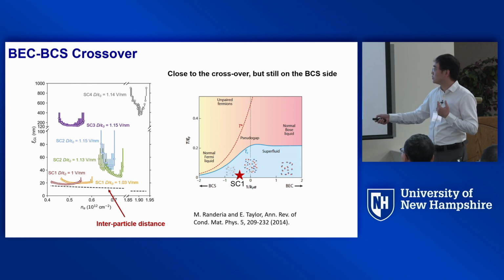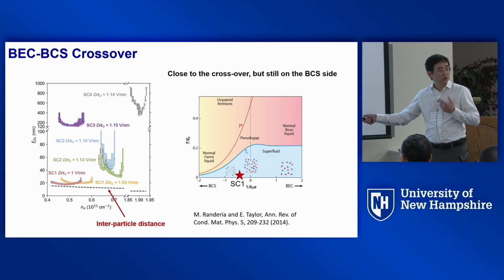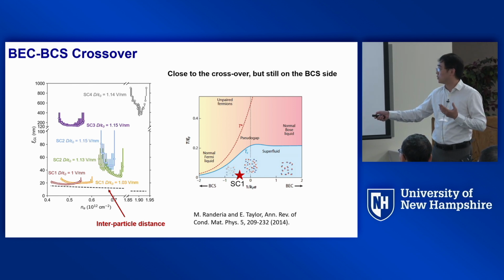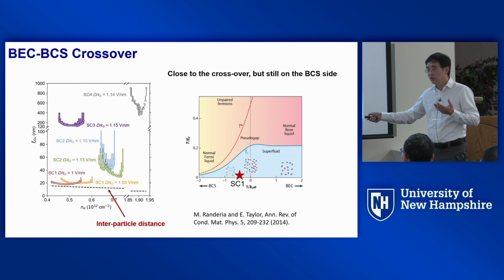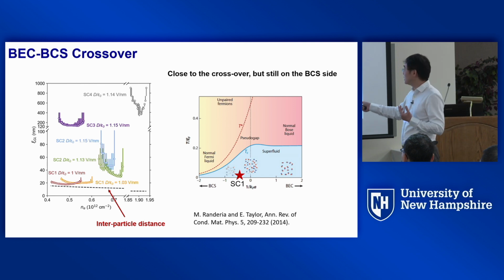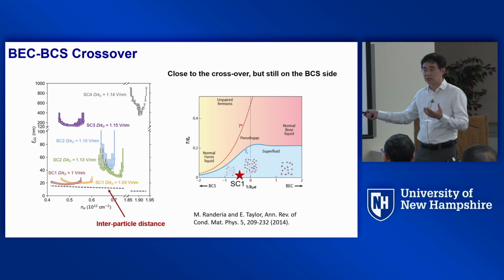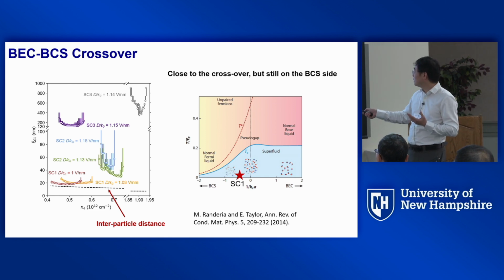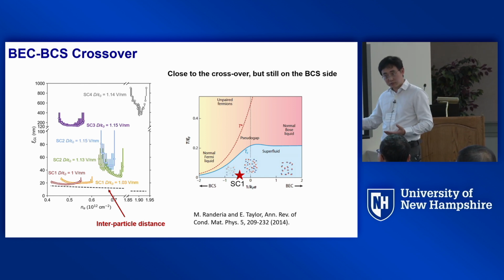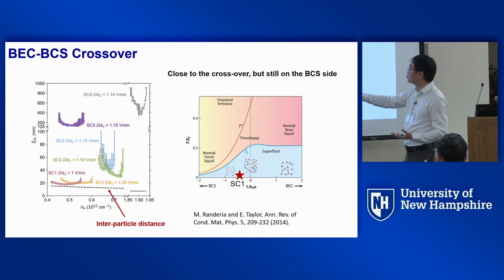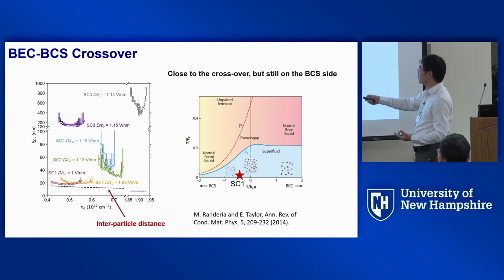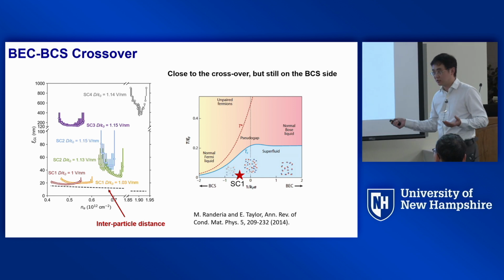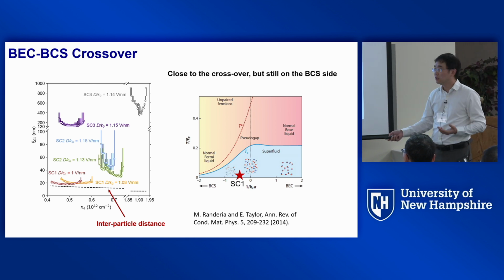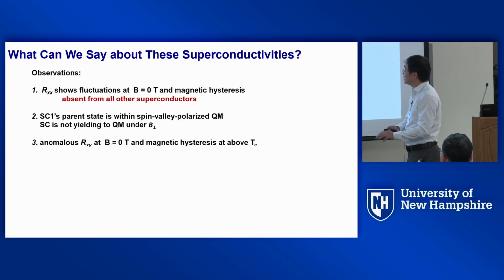And you can compare that to the interparticle distance, which is drawn here as the dashed line. And you find that SC1 has a coherence length that's really close to the interparticle distance. And that brings us to this BCS-BEC crossover picture where the superconductivity is close to the crossover, but still on the BCS side. Okay, while other more trivial superconductors are deep in the BCS side because the coherence length is much longer. Okay, so what can we say about this superconductivity?